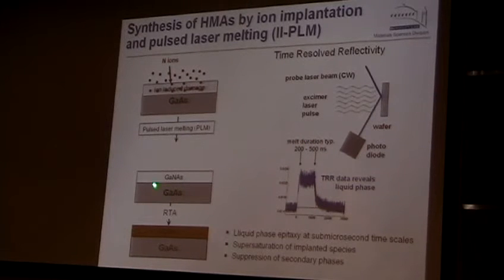The sample atoms will fly away. So there is a kind of narrow range of thicknesses here we can synthesize. But what we do is we basically have implants with different energies and try to keep uniform distribution. And what's the regular thickness? This would be about 0.1 micron.